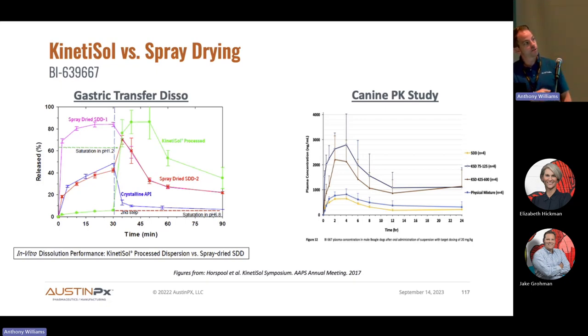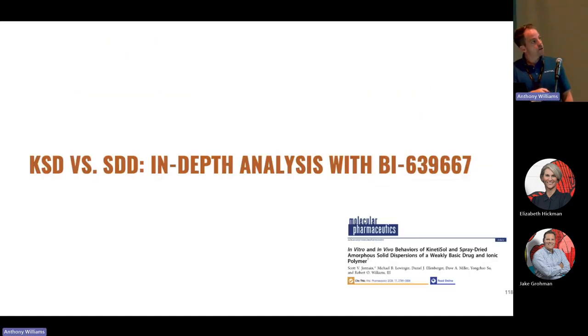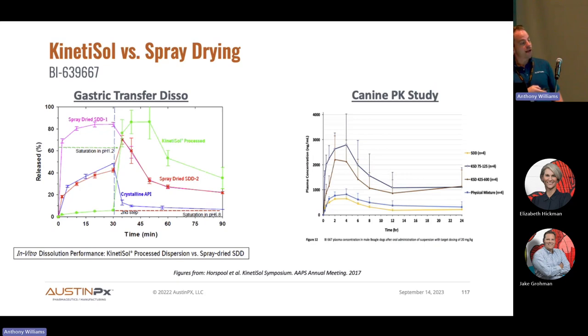So sure enough, this translated into a canine PK study where once again we saw, with different particle size versions of the KinetiSol material, significant increases in exposure relative to the spray dry dispersion. Dana mentioned that there are some instances where the recrystallized spray dry dispersion performs worse than the physical mixture, and this is one of those. The dispersion actually precipitated out from suspension and in the gastric environment so catastrophically that I think either the particle size increased or you've got aggregates that are even more slow to dissolve than the dispersed physical mixture.